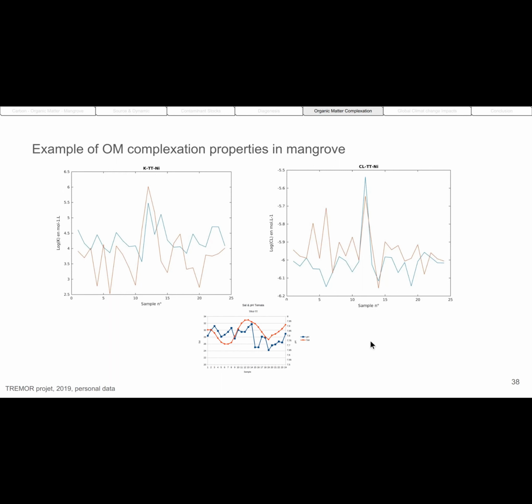But what we can use is that for each sample, we can predict what happens for the metals. So on the same sample, we also measured the total dissolved nickel. So we have the variation of nickel during the tidal event. And we used this complexation data and the concentration of all major cations, anions, etc. in the water, the pH, and we calculated the speciation of nickel in this water.